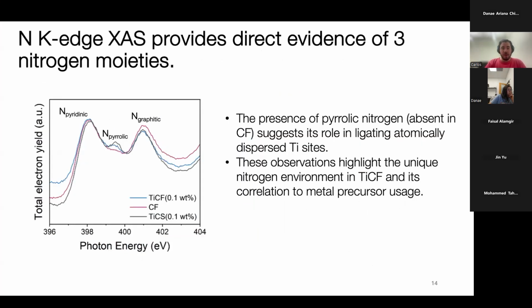Then we did N K-edge XAS, which provides direct evidence of three nitrogen moieties. You can see that in the red line over here, that's your carbon nanoflower without any titanium doping. And then the black and blue lines are titanium carbon nanoflower and titanium carbon sphere.